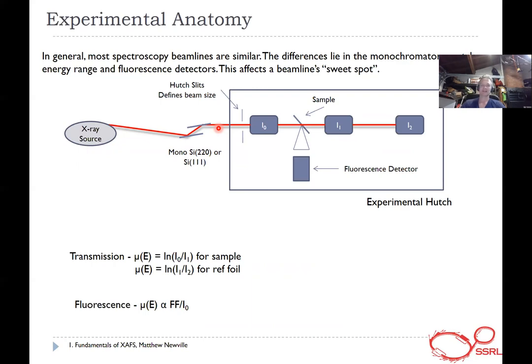4.1's a hard x-ray beamline. You have your x-ray source, which in this case is a synchrotron, obviously. You get white beam or collimated beam from a mirror if your beamline does that. It bounces off a silicon crystal. At SSRL, generally it's a silicon 220 or a silicon 111, and it comes into the hutch through some slits, through I0, hits your sample, and if you're looking at fluorescence, your fluorescence detector will generally be at perpendicular to the beam, then I1 and I2.